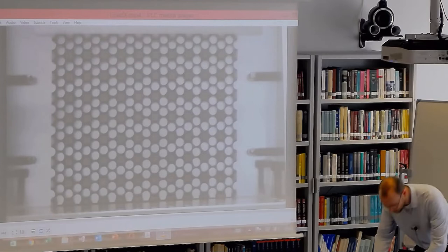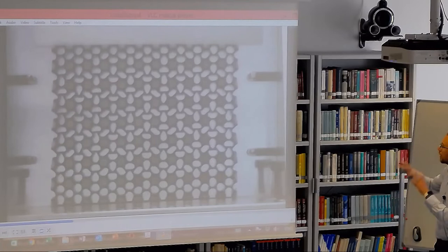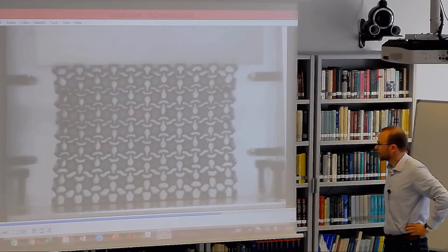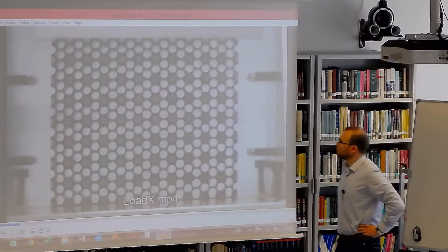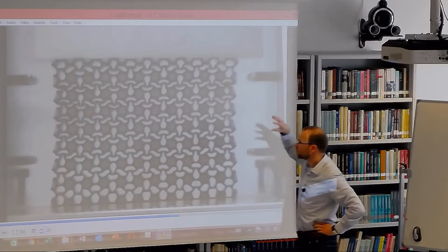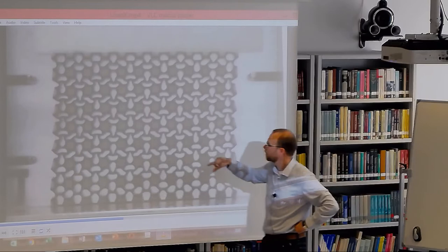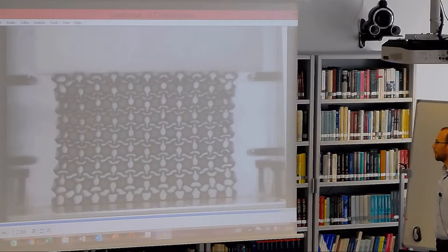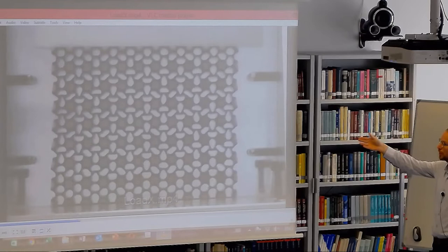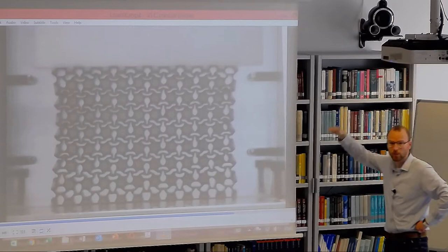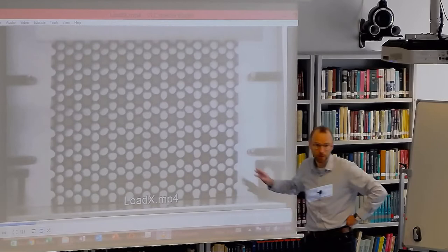Now we're going to compress it, and of course the void will collapse and rearrange into something different upon instabilities. In the first stage, they create new symmetries here. Then we continue to push, and these stiff inclusions destroy in a way the pattern that we created in the first stage. So there's a sequence of different microstructures we travel from one to another. Of course, in this system with the void pores, the material is expected to show a negative Poisson ratio. We compress in one direction, and it may shrink in this direction, depending on how we constrain it here. The boundary may affect that. So we will have negative Poisson ratio behavior in this system.